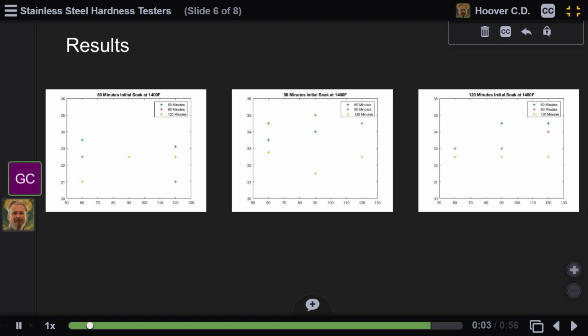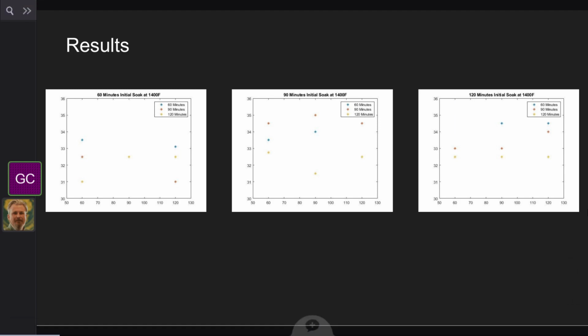The graphs shown here help paint a better picture of the results. With the 60-minute initial soak at 1400 degrees, it doesn't give quite enough time for internal stresses to build up in the sample, yielding a lower hardness all around. The 90-minute initial soak gives just the right amount of time for the internal stresses, and with the 90-minute secondary soak, it gives enough time to anneal those internal stresses to the right point too, to give the best hardness. A 120-minute initial soak at 1400 degrees is too long. The initial stresses are formed and then relieved later in the secondary soak, causing it to be not as hard but more tough.